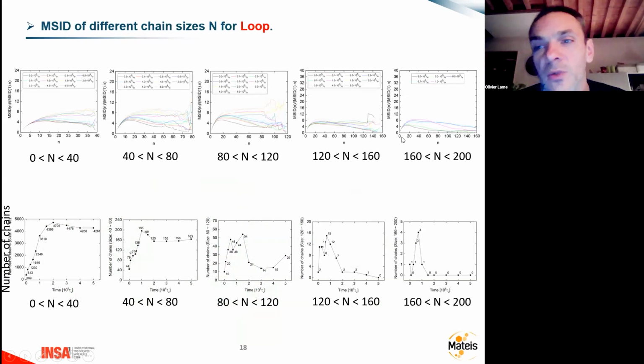And for the internal structure, the MSID, the internal distance, we see it's different. It seems to decrease with crystallization. It's not a straight line. It's not a plateau. So it means that the loops are in a situation which is not the equilibrium. It's difficult to know what kind of role it can play on the mechanical properties, but it's clear that it's not at the equilibrium. So it's maybe an important piece of information that we will have to correlate to mechanical properties, which is not obvious, of course. But it means that the ends of the loops are too close to each other compared to what they should have been if the crystallite didn't exist. So it's a non-equilibrium situation for this kind of chain.